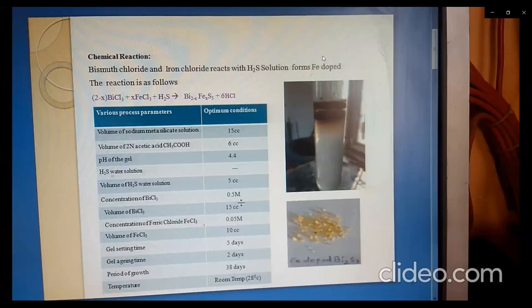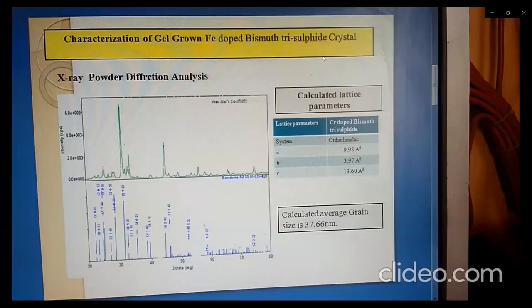and various growth process parameters. The grown crystal was characterized by XRD analysis. The XRD pattern shows sharp peaks. By using Scherrer's formula, the calculated grain size of the grown crystals is 37.66 nanometer. By using XRD data and comparing with standard data, the d values and 2 theta hkl values match well. Using the relation 1 upon d square is equal to h square upon a square plus k square upon b square plus l square upon c square,